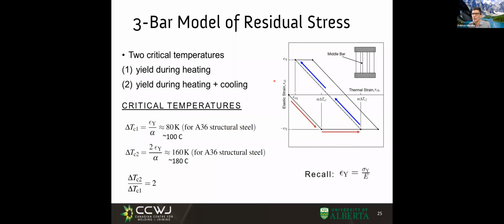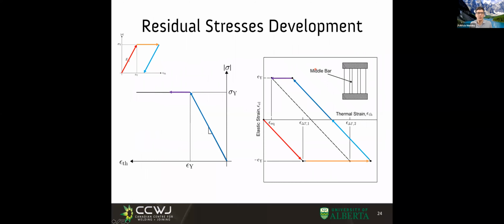So, what do the red, yellow, and blue lines mean? Okay, let's see here. Here we have total strain in the bottom, and in the vertical we have elastic strain. The red line means we are loading elastically. Then the orange line here means we keep loading it because the temperature keeps increasing, but it's plastically. And this increase in strain we see is all the plastic strain. So this is the initial condition. This is increasing temperature. This is still increasing temperature. And then this point is the point at which we reach maximum temperature.